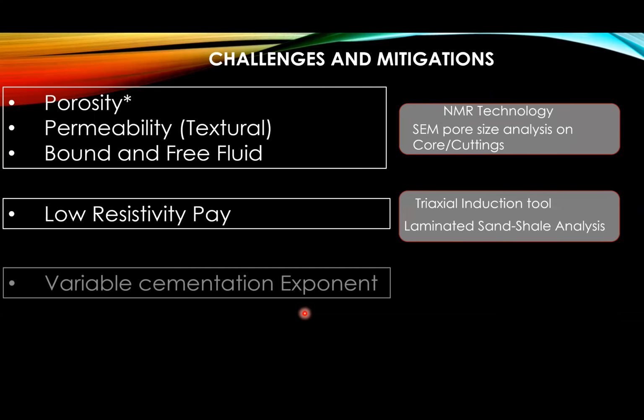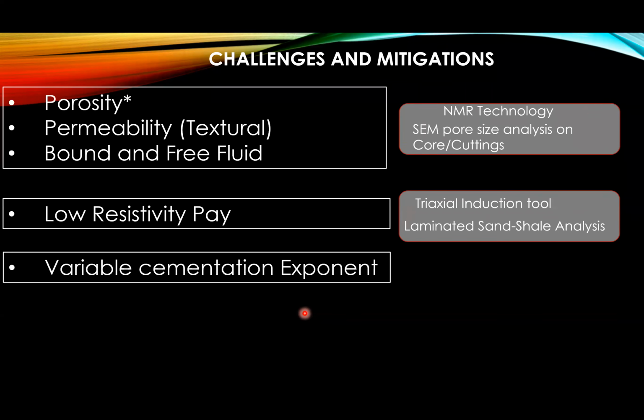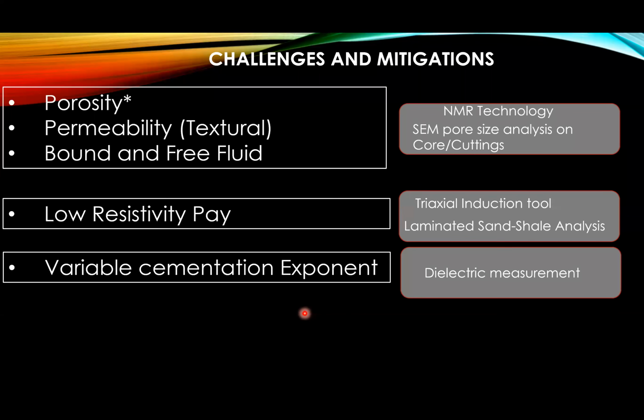And then a variable cementation exponent. You're now talking about the saturation equation, for example, Archie's equation. You remember that m, the cementation exponent, can vary in these rocks. Ideally, we take only one number. Mostly we use the number 2 in our equation, and actually it's not always 2 in these tight gas sands, and it can vary quite significantly. And that can be determined. Actually, we can run the dielectric tool again here for that determination.